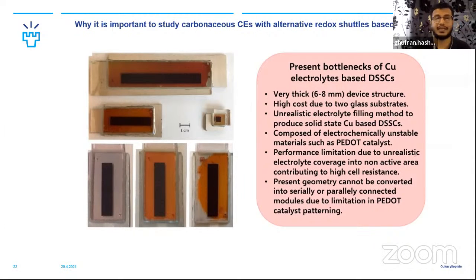And also, at the moment, because it is reported with the PEDOT catalyst, under harsh conditions the chemical inertness of the PEDOT catalyst has not yet been established, despite some initial stability reports, because in the presence of harsh solvents, this PEDOT as a conducting polymer catalyst can dissolve. There is a study with a cobalt redox couple based electrolyte, where it was shown that the cells degraded under stressful conditions. So the stability of the PEDOT catalyst has yet to be established, and more studies are expected in the near future.